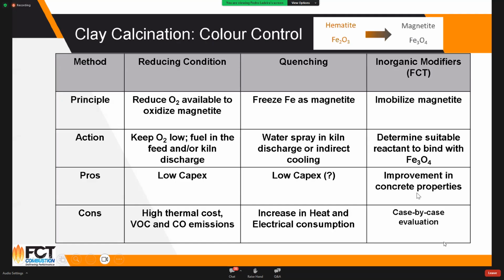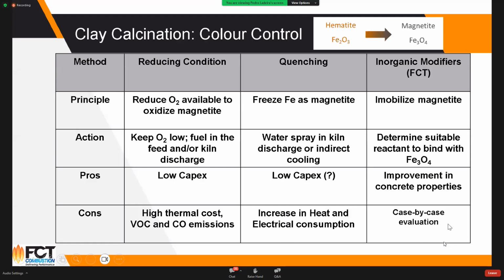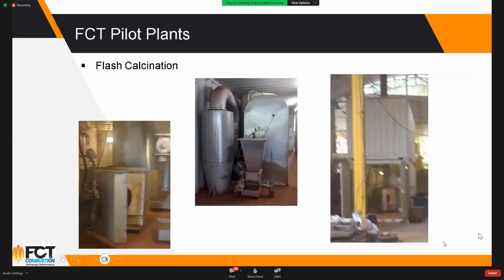And what we see as one of the most important pros is that you normally have an improvement in the concrete properties, one of which is that you reduce blaine. By reducing blaine, you know that the water demand is going to be lower, so the demand for plasticizer reduces and so on. What are the cons? Well, we cannot say. It's a case-by-case evaluation. But generally speaking, in terms of CO2 footprint compared with the other methods, we're better off in this one.